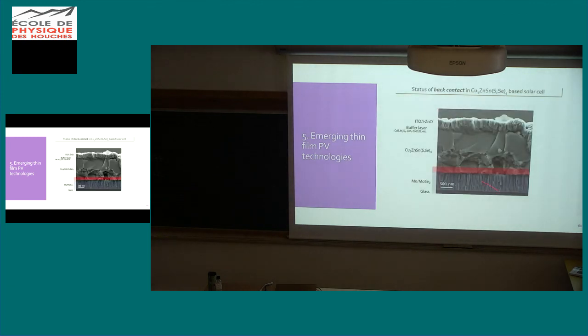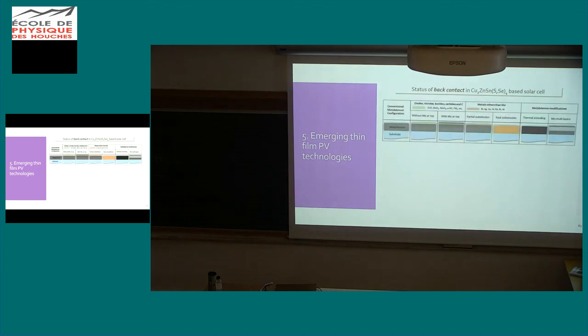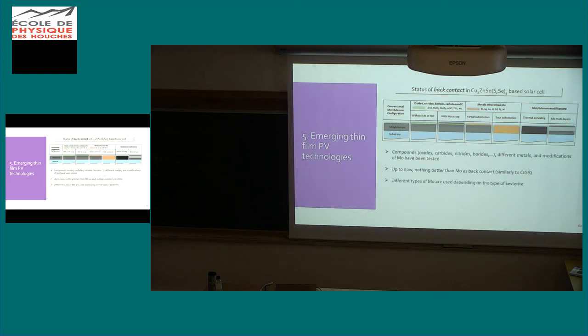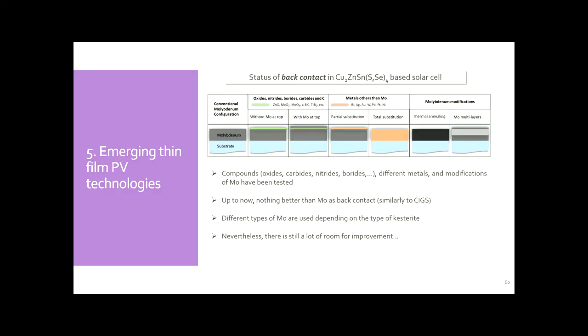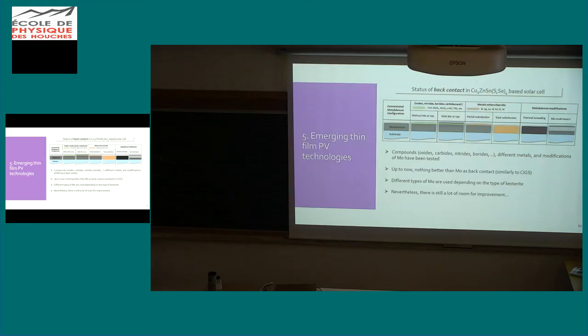So just to show you briefly, in terms of back contact, believe me, we tried anything you can imagine, anything. And nothing works better than molybdenum. I can show you hundreds of examples in the literature about substitution of molybdenum in CZTS by another contact in order to improve the back contact properties, but all of them fail. So molybdenum is still the best option for this technology.